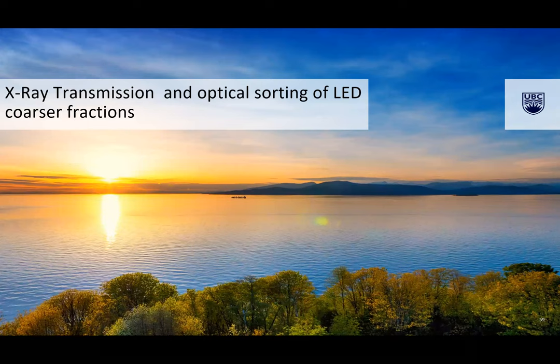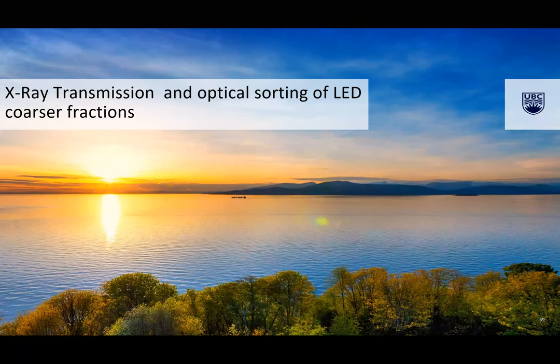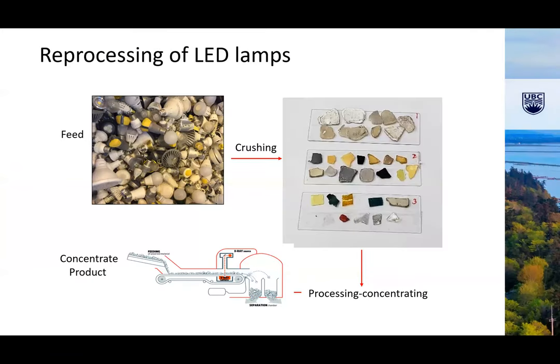When we look at the cases where, instead of grinding, shredding to fine sizes, we can somehow dismantle or lead to a process where the crushing is not very intense and we can end up with larger pieces of our LED, as we did here by just using a hammer mill, we ended up with much coarser particle sizes. Then another option becomes available, such as sorting. Sorting usually is very efficient at coarser particle sizes.